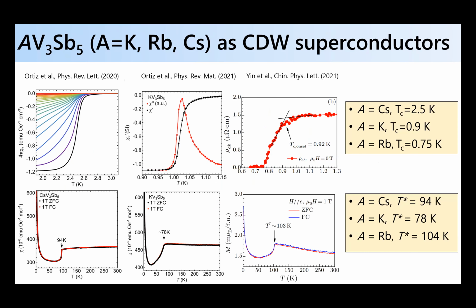Okay, and these systems are charge density wave superconductors. Okay, so all three compounds show a charge density wave instability at around 100 Kelvin. So the details vary depending on what the alkali site is, but it ranges between 78 Kelvin to 104 Kelvin as you change the A site. And all three systems are also superconductors, with the highest TC being about 2.5 Kelvin for the cesium compound.